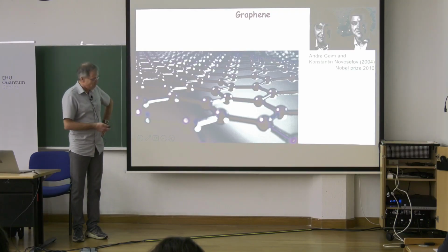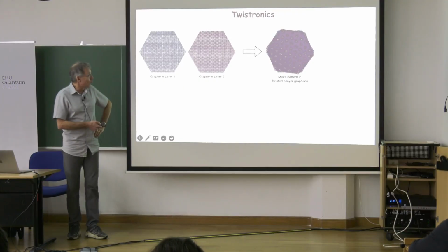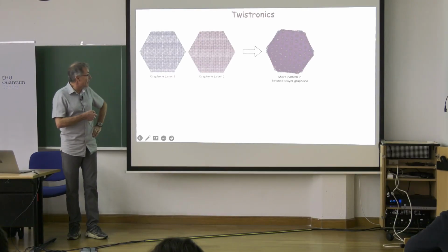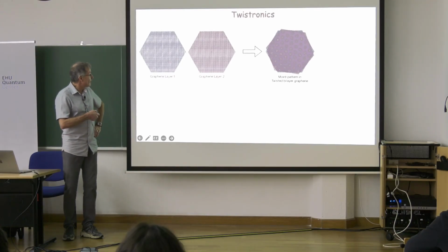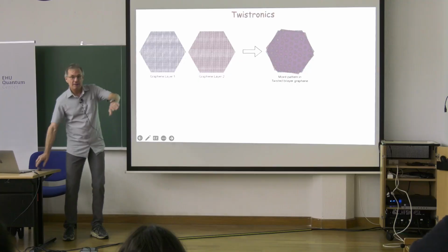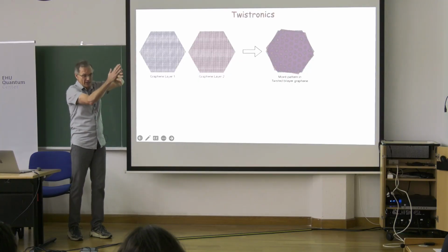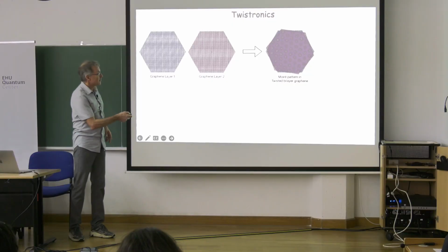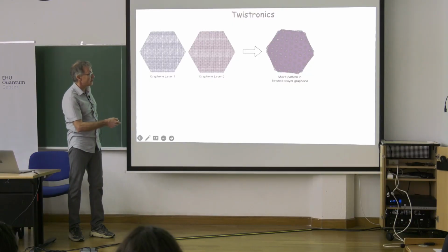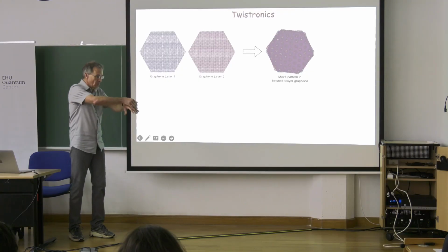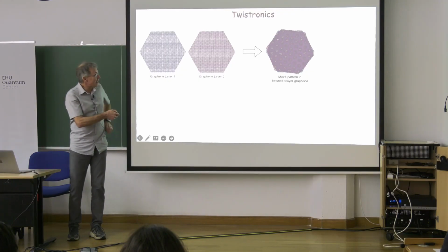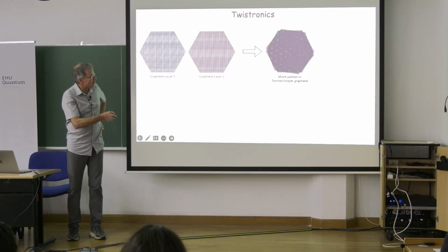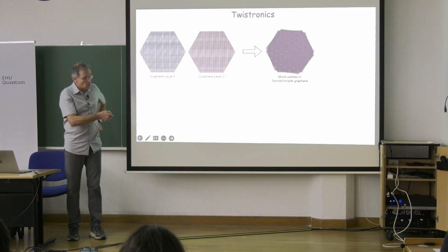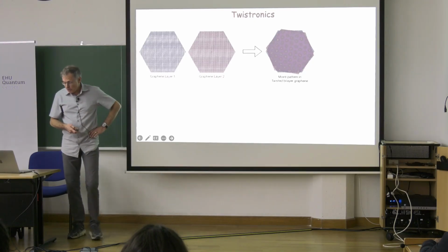Now, another step which is important for us was so-called twistronics. If you take one layer of graphene, you put another layer of graphene, and you rotate them by some angle, then you get this kind of picture, which is called a moiré pattern. It has a superstructure with a supercell, which has a size depending on the angle.